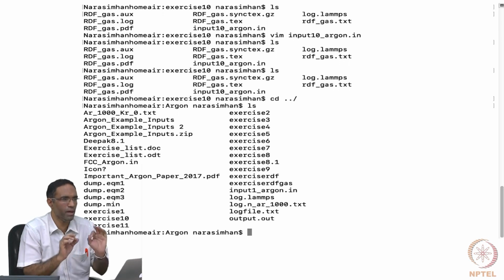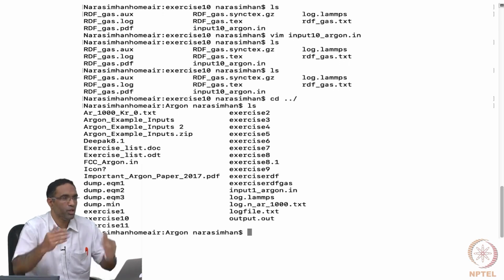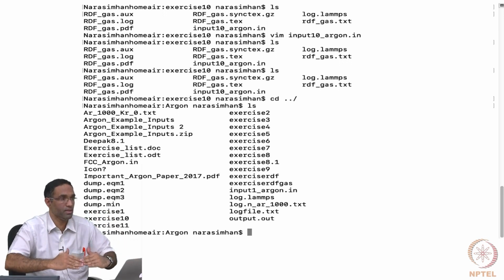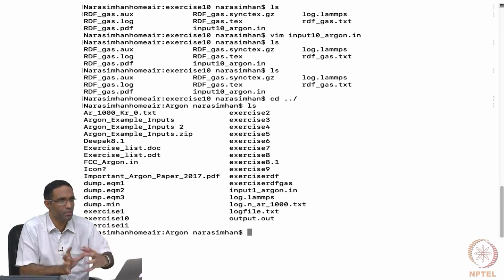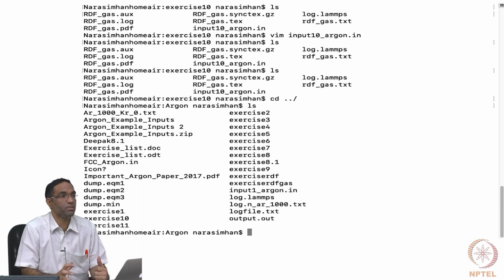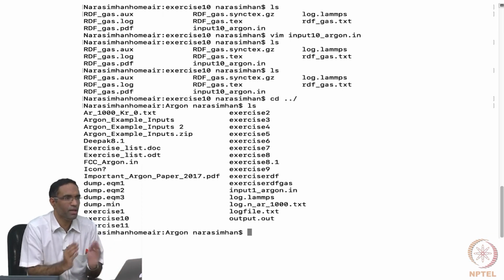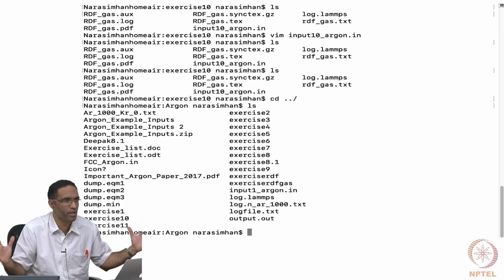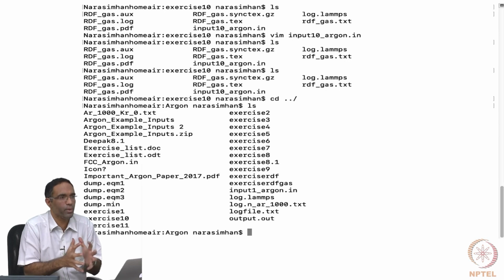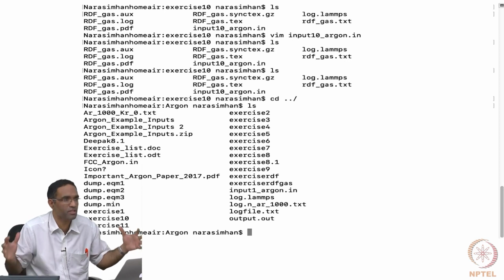It is not really a barostat. It is not something that is going to maintain the pressure over time. During the process of minimizing the energy of the system, it does a little bit of adjusting of the box size. That's it. After that, mostly you still have to do NPT. But if you're starting off from a really far off configuration, this can be a crude way to bring the system to approximately the size that you want.